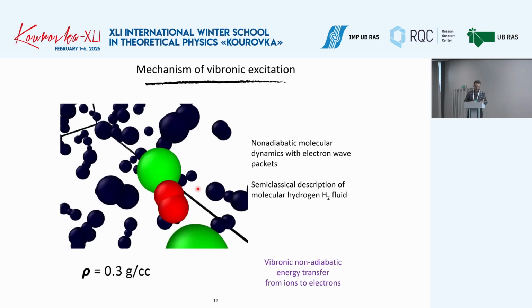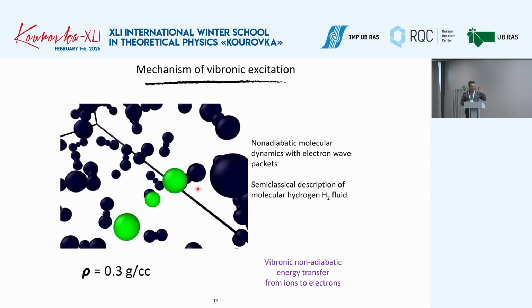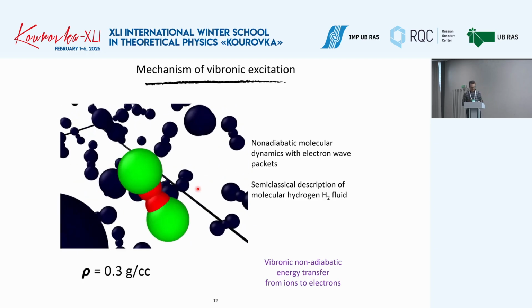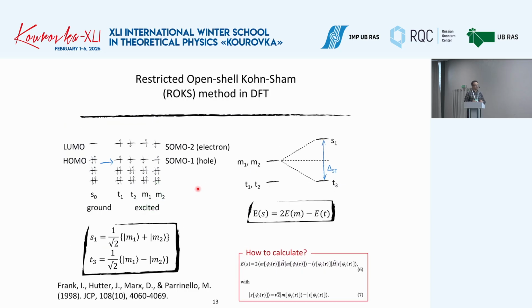So in this model, we see this process qualitatively. And then we use DFT to consider the first lowest excited state in more detail. So this ROKS method uses quite a simple ansatz. We can express the wave function composed from Kohn-Sham orbitals as a sum of two determinants. And in this model, we can solve this electronic structure model quite efficiently and fast for molecular dynamics. And we obtain two higher singly occupied SOMO orbitals. The highest one represents an electron, and the lower one represents the hole.